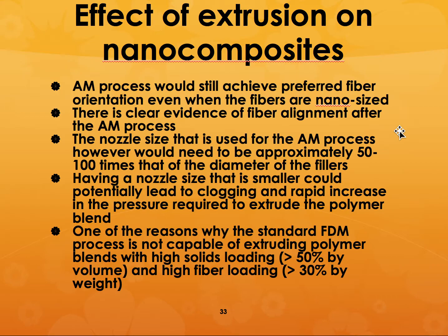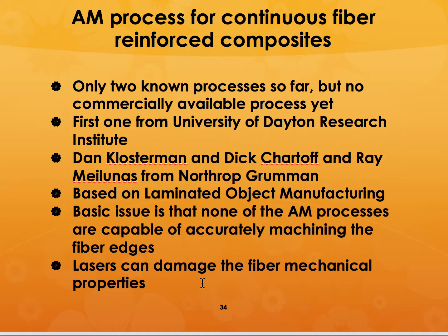And so what happens is that when you have such a small nozzle, any amount of clogging or the fibers going crosswise, which could be very easily possible, can easily clog the nozzle and jack up the force required to extrude the material through that nozzle. So this is the reason why the standard fused deposition modeling is not capable of extruding polymer blends with high solids loading: 50% by volume if it is just particles, and fiber loading which is greater than 30% by weight. So it's really not possible using the standard fused deposition modeling or even the extrusion freeform fabrication.